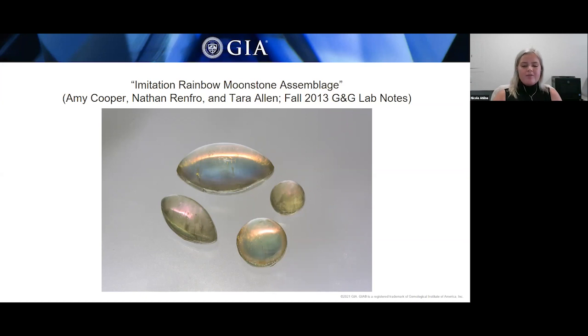That coating prevented readable RIs for both the top and the base, but in polarized light, a bullseye optic figure was collected on that base, confirming it to be rock crystal quartz. It also has natural inclusions such as fluid inclusions and reflective particles, confirming that the base was natural rock crystal quartz. And then the top was identified as gypsum through Raman spectroscopy.